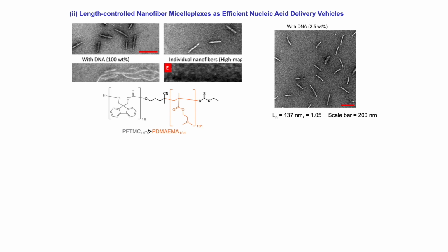So we made lots of different lengths, and we use a plasmid DNA that, when it's delivered into a cell, it expresses luciferase, which gives you luciferin, which is a green fluorescent molecule. It's actually the one that's used for the fluorescence from fireflies. Then to judge the success of the incorporation of the DNA into the cell, the transfection efficiency, you can use fluorescence to measure the transfection efficiency.